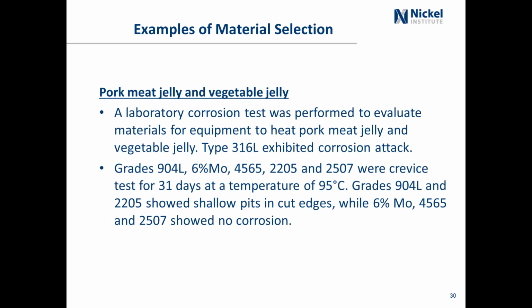Pork meat jelly and vegetable jelly is another example where there's a lot of chlorides present in the production of these foods. A laboratory corrosion test was performed to evaluate the materials for equipment to heat pork meat jelly and vegetable jelly. Type 316L exhibited corrosion attack. But then steels with higher PRENs like 904L, 6 moly superaustenitic, 4565, which is another type of superaustenitic, duplex 2205, and 2507, which is a super duplex stainless steel.